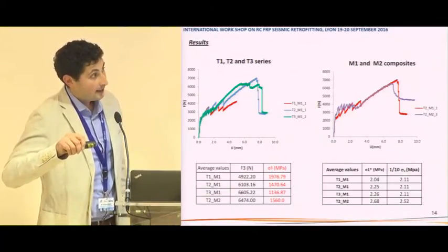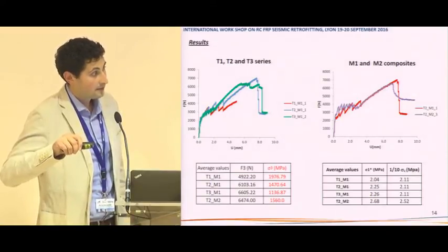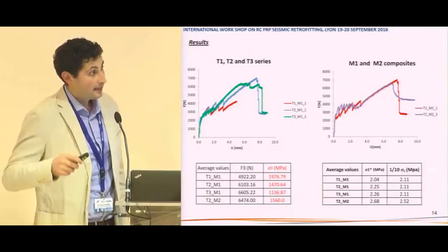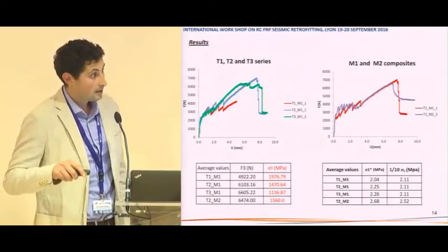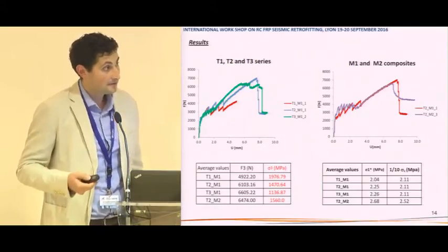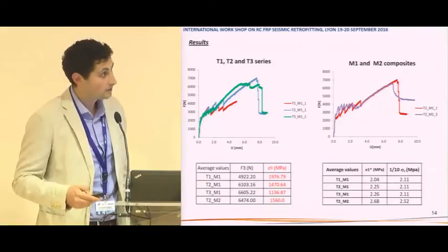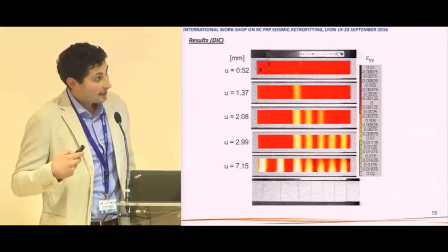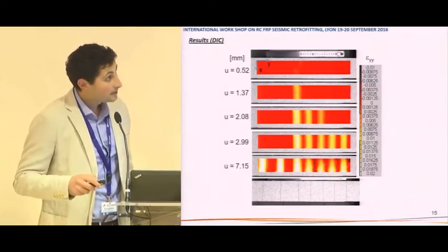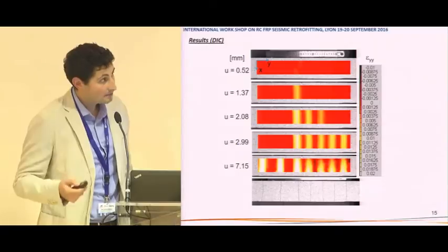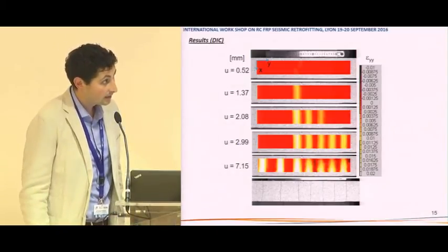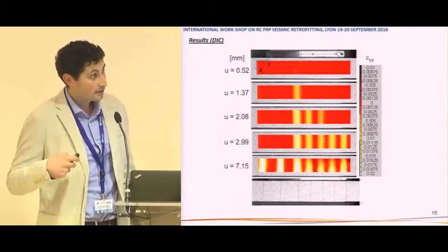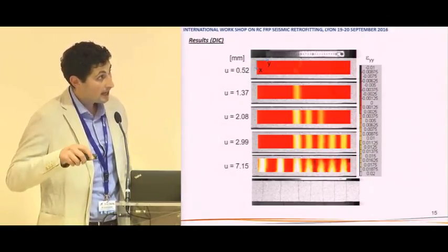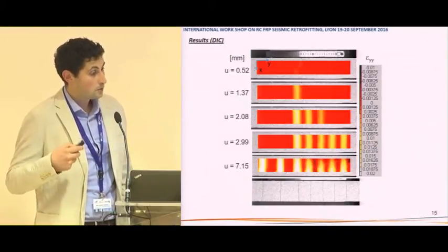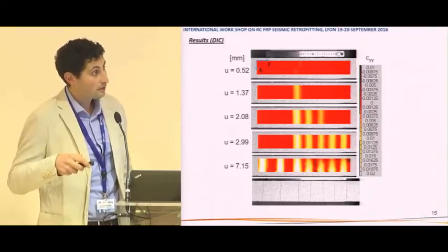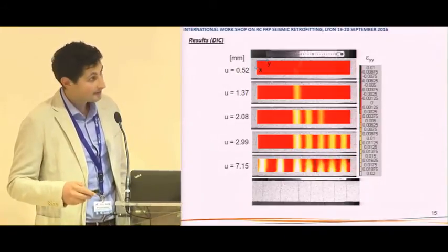If we divide the force obtained when the first crack happened by the total cross-section of the composite, we can find the tensile strength of the mortar, and it is logical. The analysis by digital image correlation has permitted us to define the displacement field on the whole surface of the specimen. The derivation of the displacement field has permitted us to obtain the strain field and to analyze deeply the evolution of the cracks during the test.